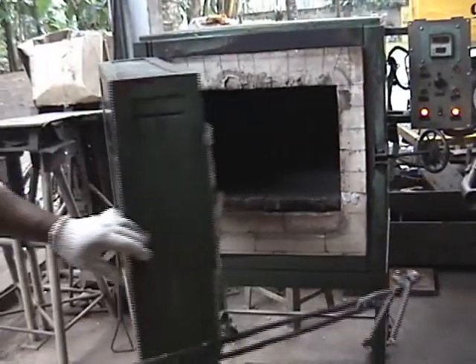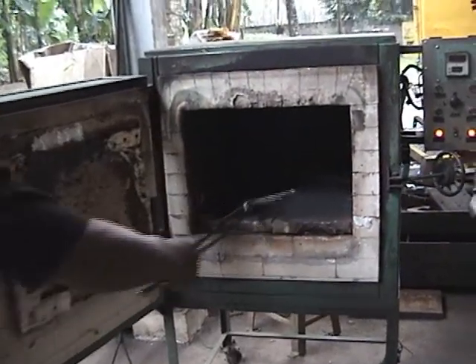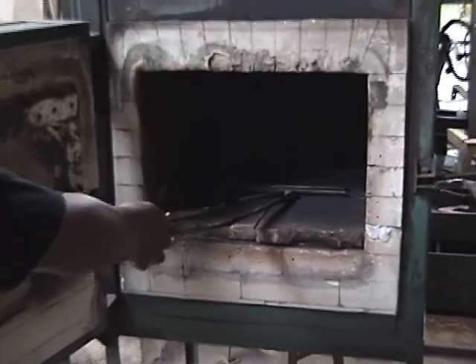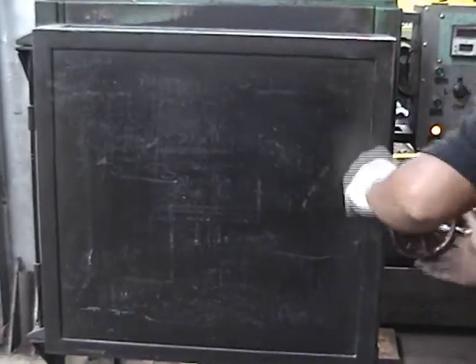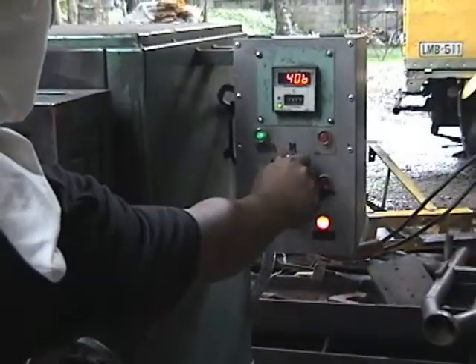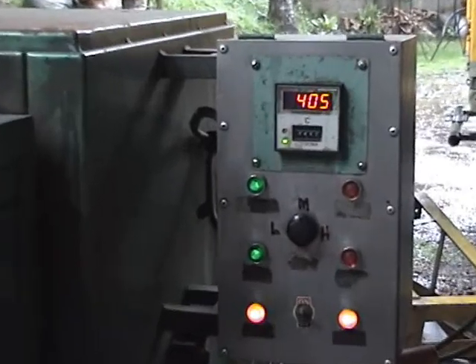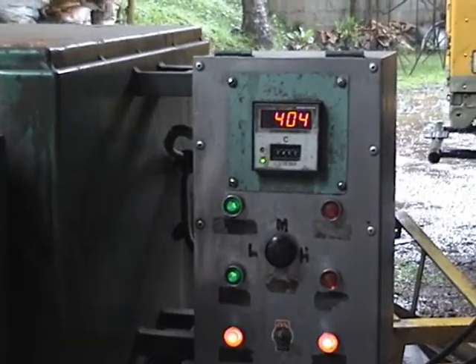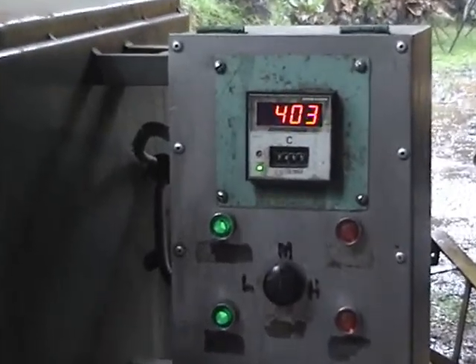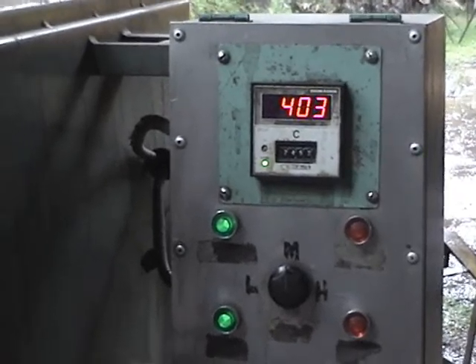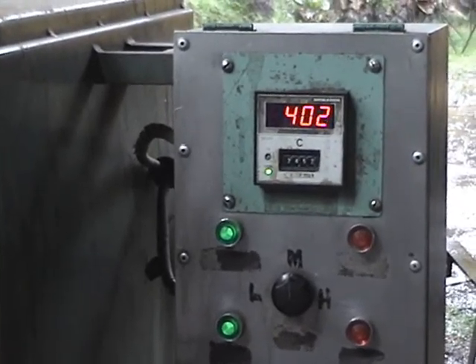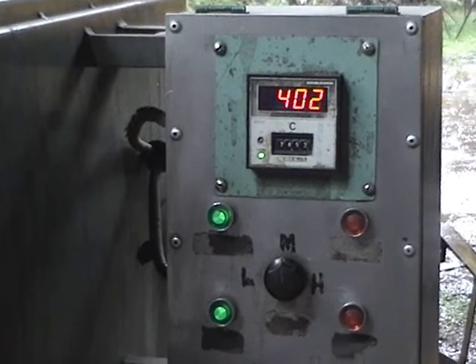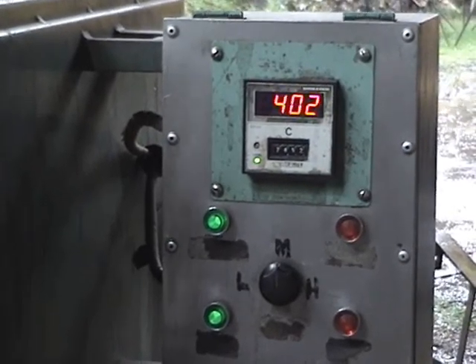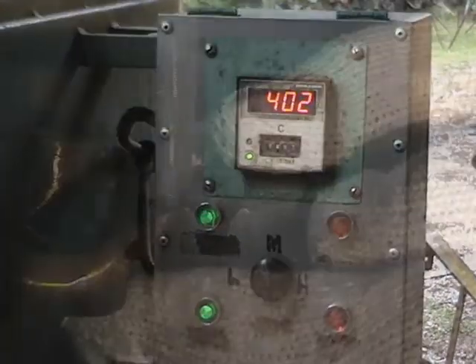The tool is then put into the tempering oven, where it is brought slowly up to the proper heat. Held at that heat for several hours, then the oven is turned off overnight so that the tool cools very slowly. This is called tempering, and it brings the Rockwell hardness back down to between 63 and 67, which, in our opinion, is perfect for a nipper blade.